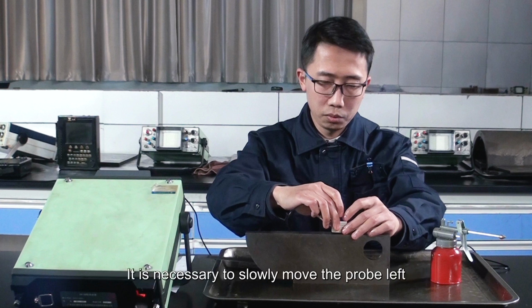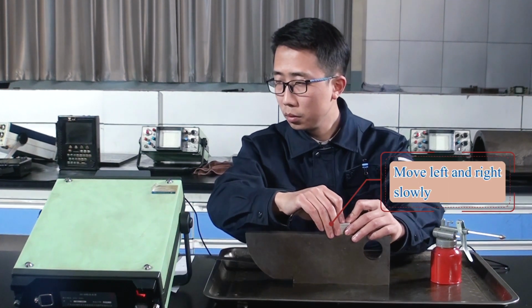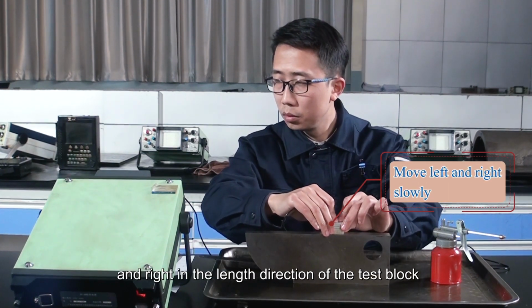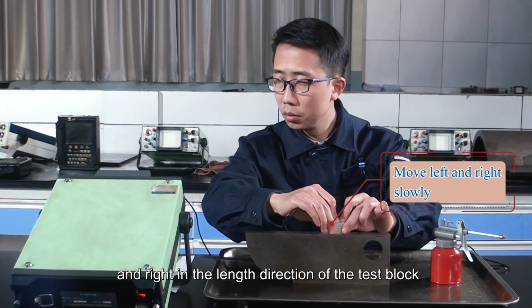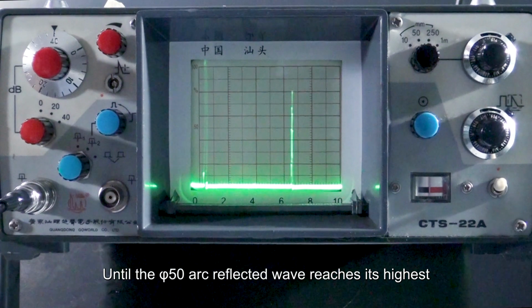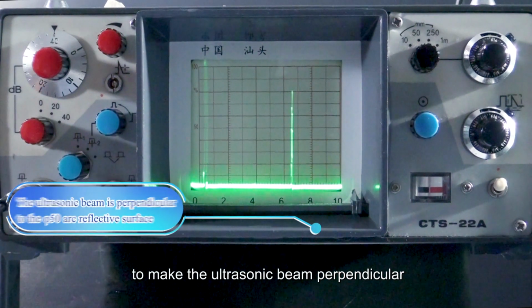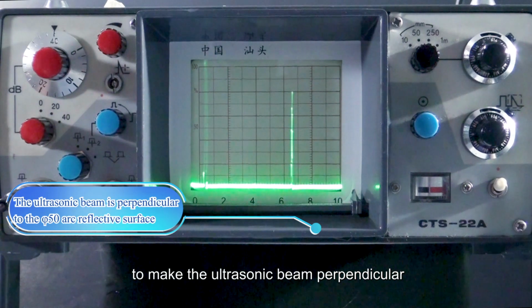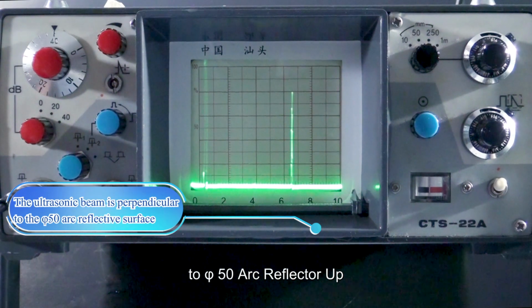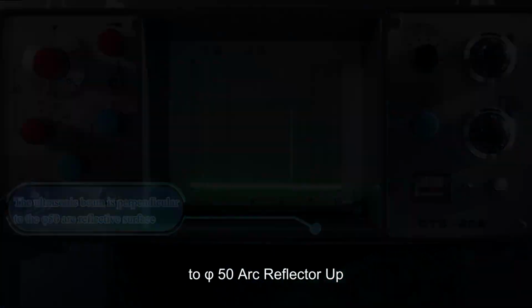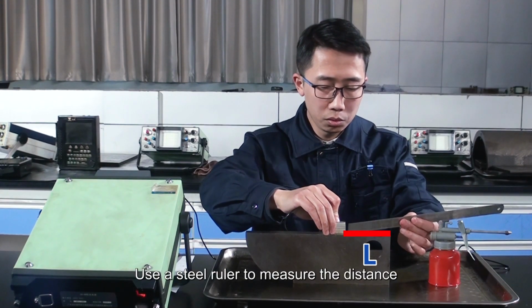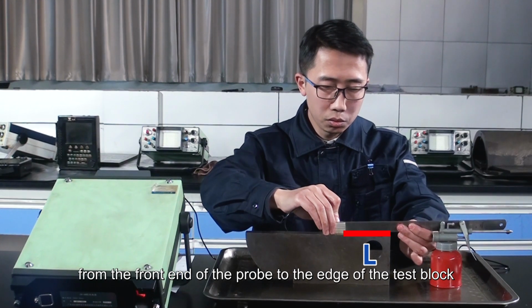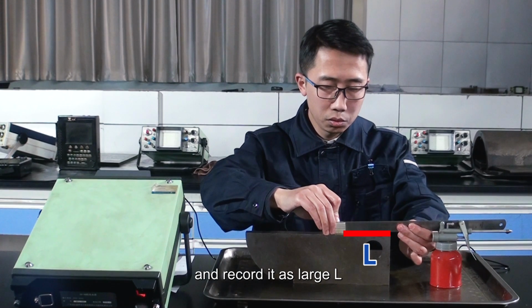It is necessary to slowly move the probe left and right in the length direction of the test block until the φ50 arc reflected wave reaches its highest, that is, until the ultrasonic beam is perpendicular to the φ50 arc reflector. Use a steel ruler to measure the distance from the front end of the probe to the edge of the test block and record it as L.